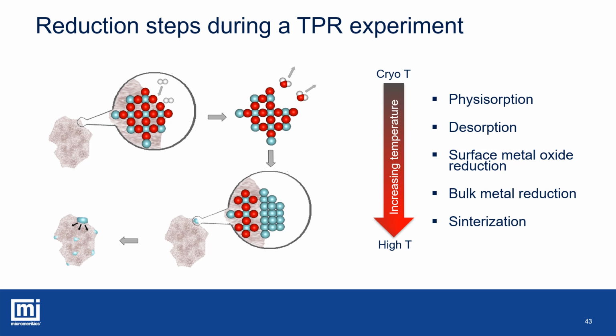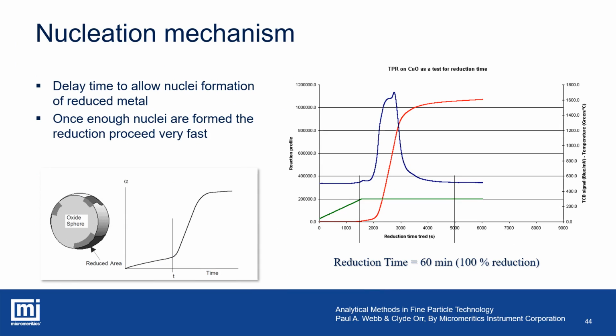The reduction of a metal oxide can be described by two models, nucleation and contracting spheres. It is important to consider that the reduction mechanism can be different for the pure metal oxide and the supported metal oxide, because the metal-support interaction can modify the reduction mechanism. The presence of a second metal or a dopant also can modify the mechanism. Finally, the presence of a spillover phenomenon might accelerate the reduction process thanks to the migration of atomic hydrogen through the support.